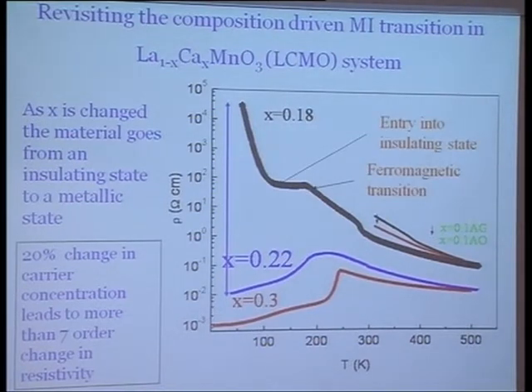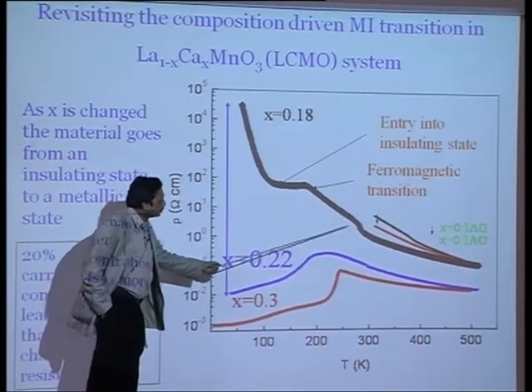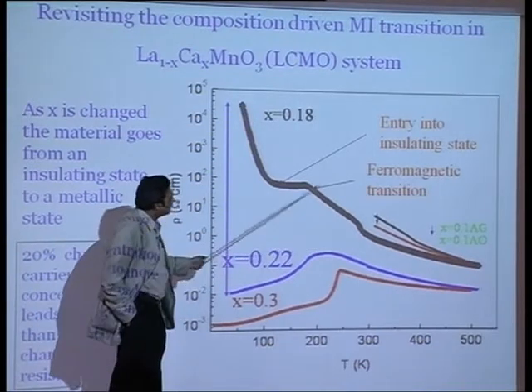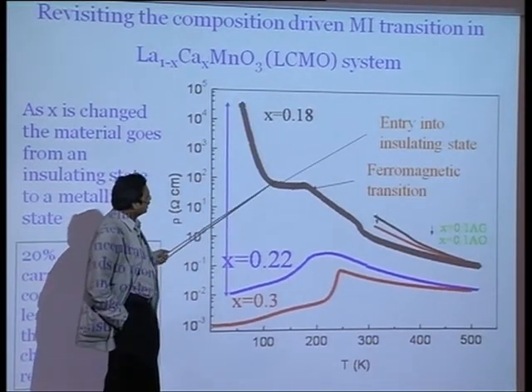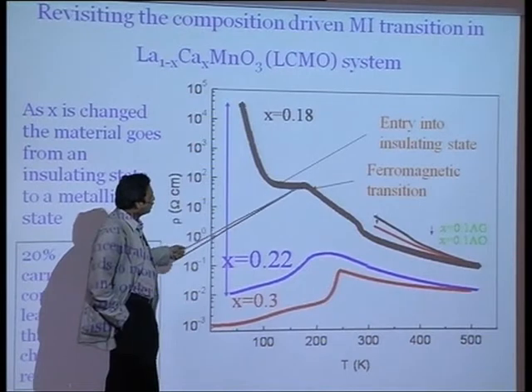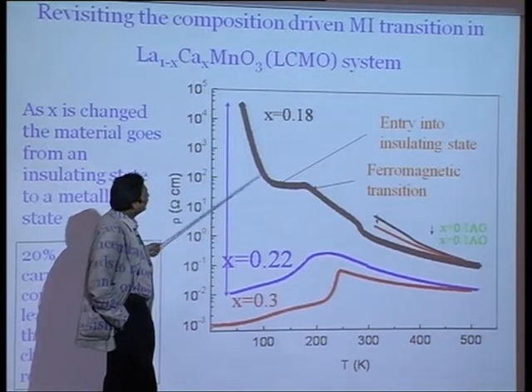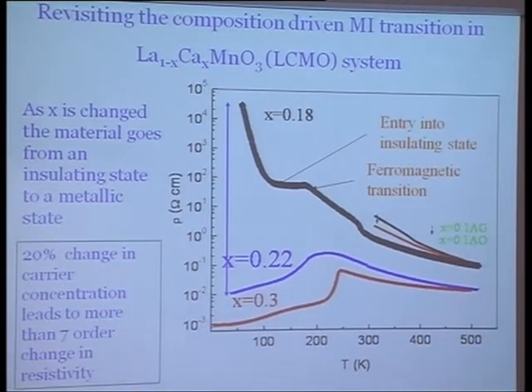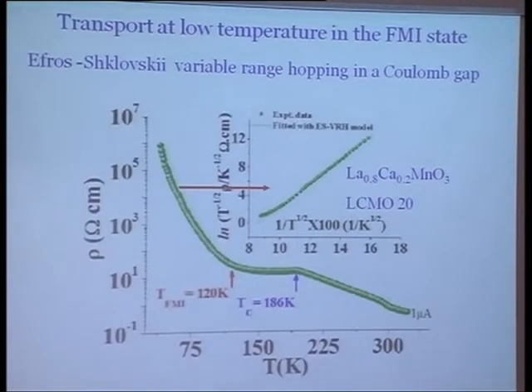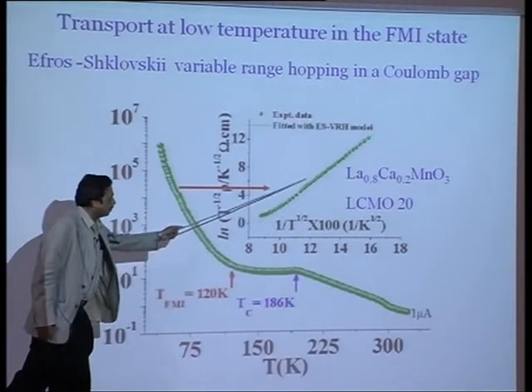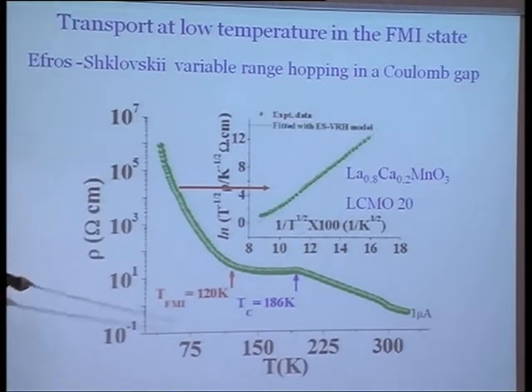What I mean by ferromagnetic insulating state is that in this material, the resistance is rising. There's a ferromagnetic transition over here. In this kind of mixed phase over here, the resistance comes slightly down or even flat, and then it goes into an insulating state, and that is the ferromagnetic insulating state one is talking about. And in that state, if you take the resistance, you find that it follows the famous Efros-Shklovskii kind of hopping region. So this is the region one is talking about.